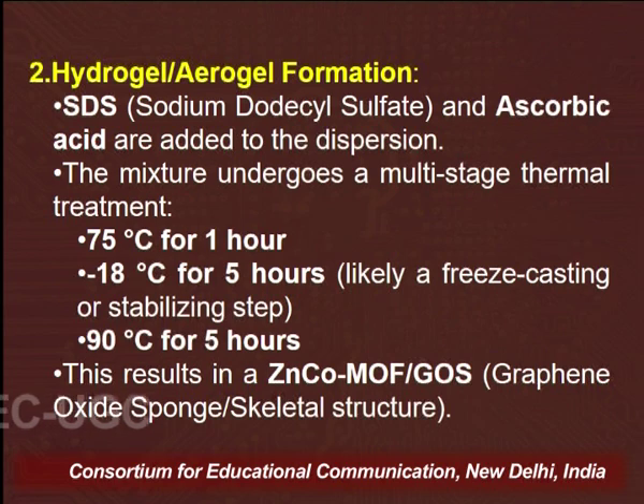This mixture undergoes a multi-stage thermal treatment: 75 degrees for 1 hour, minus 18 degrees for 5 hours, likely the freeze casting and stabilizing step, moreover 90 degrees centigrade for 5 hours. So there are various thermal treatments done for preparation of the hydrogel aerogel formation. This results in a ZnCo-MOF-GOS, that is graphene oxide sponge, a sponge type of structure. First we had the fabric, we had the foam, now we have a sponge type of structure.